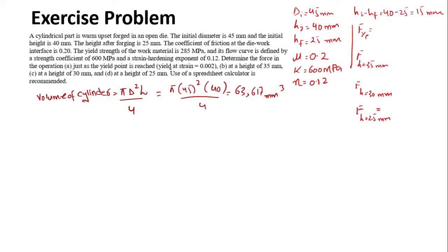Now it says at the yield point. As we have seen in the last lecture, if we don't have an exact value of yield point, we draw a line parallel to the stress strain curve at an offset of 0.002 strain, and the point where it strikes is the yield point. So as the yield point is reached, we have the strain equals to 0.002.